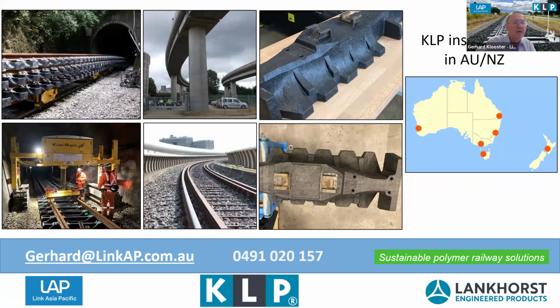You see on the left-hand side the tunnel that KiwiRail was using composite sleepers. This is a special sleeper made as low as possible, 130 millimeters high. A viaduct in the Netherlands. The benefit with the viaduct is that you can make the entire viaduct lighter because you use lighter dead weight, in that the KLP sleeper is a lot lighter than a concrete sleeper.